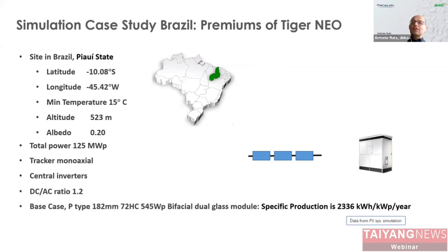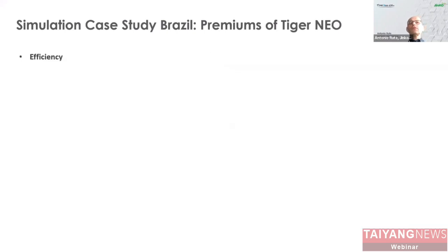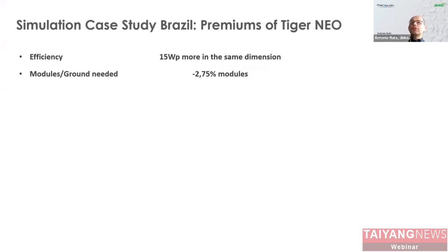In this simulation, the DC/AC ratio is 1.2, and the base case is the 182 P-type, which is a good module and has had great success in our region, where the specific production according to PV system is 2336 kilowatt hours per kilowatt peak per year. In terms of efficiency, of course, if we consider the same dimension, Tiger Neo allows 15 watt peak more in the same dimension. So practically we have a great advantage in terms of number of modules, or in case of ground needed, because we can save ground. In our case, we can put more modules, so we can add more power density in the ground that we are considering. String length is the same: thanks to the minimum temperature of 15 degrees, we can achieve 29 modules per string.